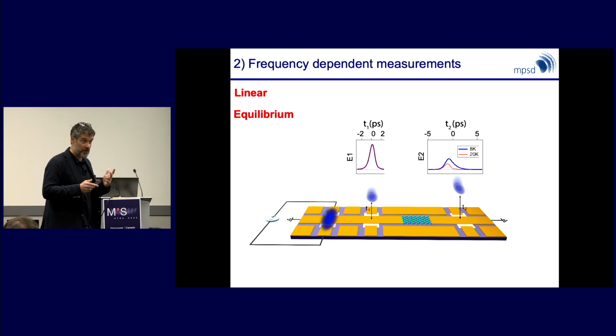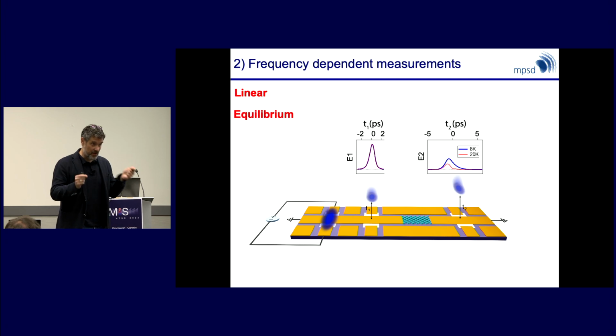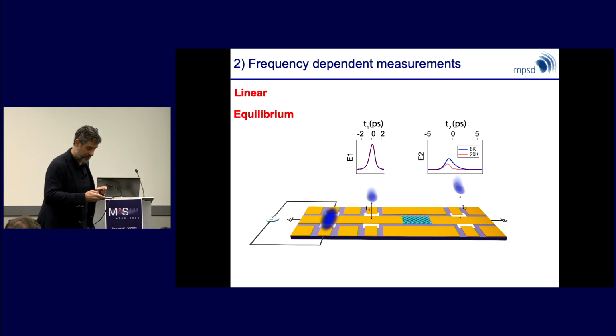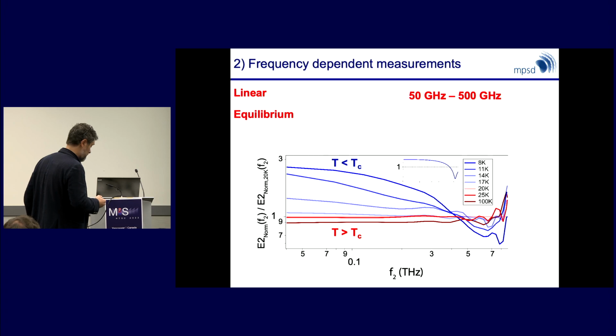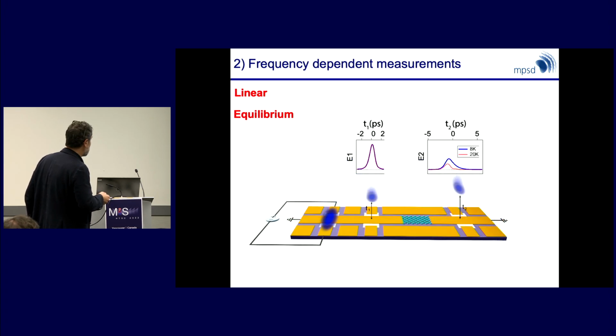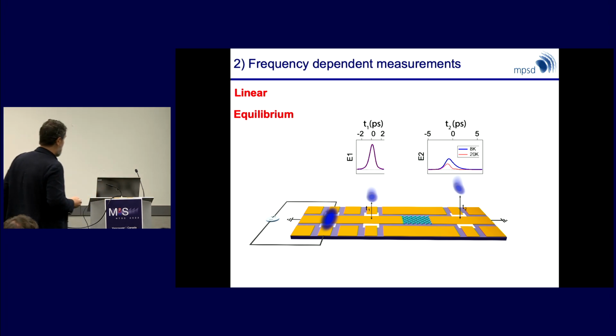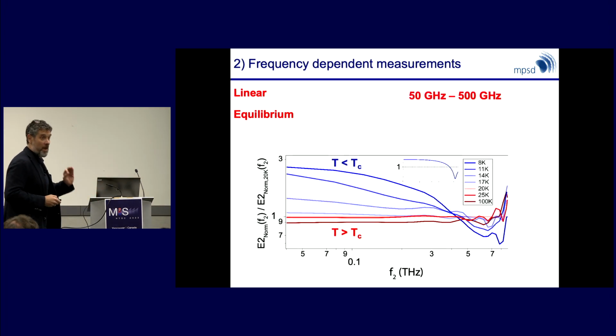So the first thing I can do is calibrate these terahertz current measurements as a function of temperature, in equilibrium. What I do is the following. I take the outgoing pulse, take the modulus of its Fourier transform, and divide it by the modulus of the Fourier transform of the incoming pulse. Perfect. So this is what I should expect in a material that I know below 19 Kelvin becomes a superconductor, because I've measured the 4-probe DC resistance.